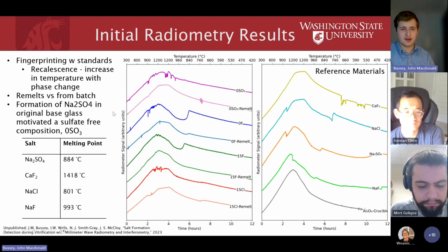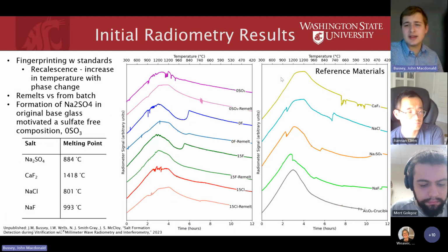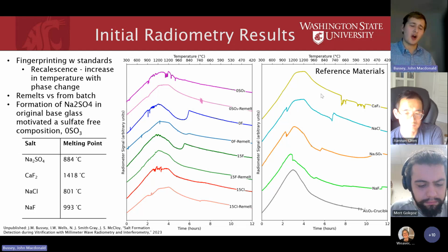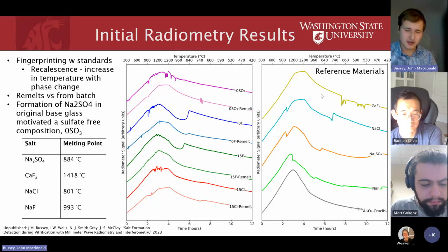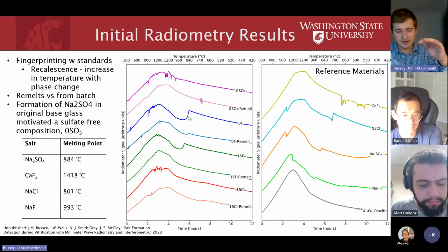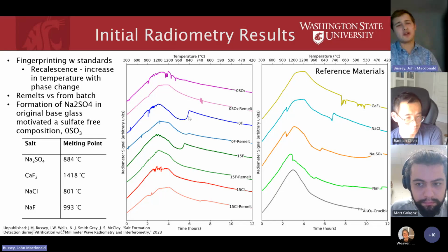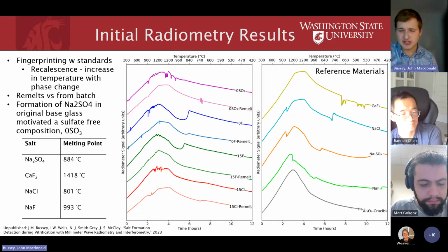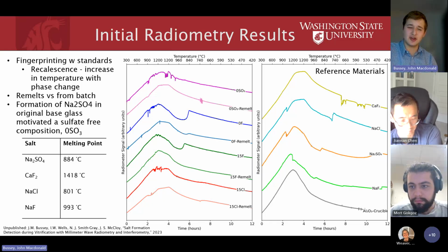So what do our results look like? So we get these curves. So before I go further, we used a temperature profile to look at this. Instead of just looking at a fixed temperature, we heated up the melt, held it constant, and cooled it down. And so for a perfect black body that had no reactions or interactions, we'd expect this to be kind of a stepwise function.